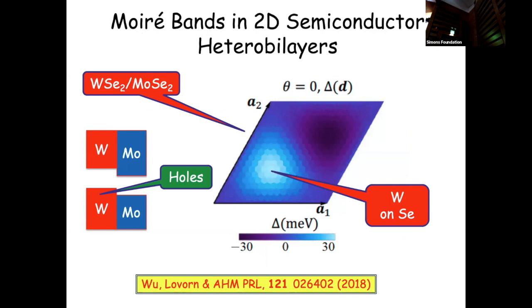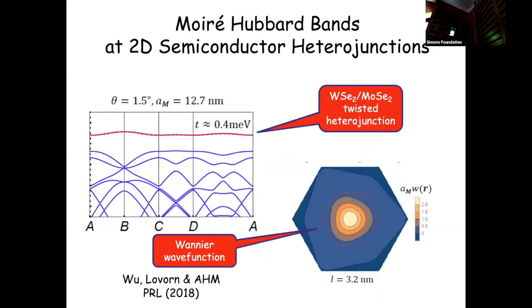As for example here, this is a tungsten diselenide, molybdenum diselenide example. The states we're interested in are at the top of the valence band, which turns out is in the tungsten. Those orbitals are d orbitals on the tungsten atoms, and the local energy goes up when they sit on top of a negatively charged ion. That's basically the physics of what produces this periodic potential, which has a typical size of around 50 millielectron volts.